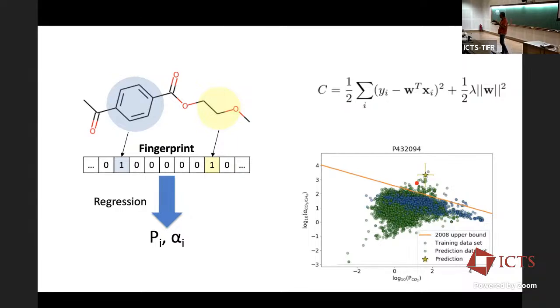The database of known polymers is 10,000, so we make predictions for 10,000. Here is one such prediction, log of permeability versus selectivity. This is currently the very best polymers, for CO2 methane separation. Most of the data falls below the upper bound, telling you that most of the polymers out there are not going to do better than the ones that have already been tested. But here there's order 20, 30, 50 polymers that are actually better.